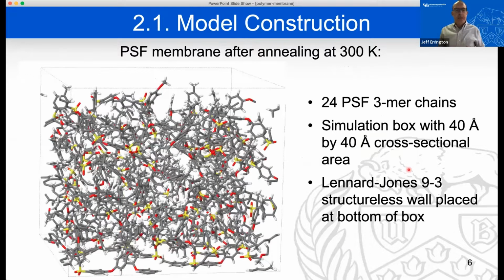So what we did was to take a simulation box that was constrained 40 angstroms by 40 angstroms in terms of cross-sectional area, a confined system. We made it, to begin with, relatively high in height. On the bottom of it, we put a Lennard-Jones 9-3 structureless surface. The basic idea was we just wanted something there to be sticky in some sense and be a place for the polymers to naturally start to aggregate, if you will. And then we put into the simulation box 24 polysulfone 3-mer chains. And we then went through a process in which we started off with a temperature of something like 1,000 or 1,200 Kelvin, and over time we reduced the temperature down to 300 Kelvin.